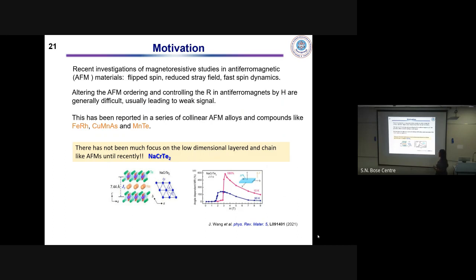One of the systems is NaCrTe2, where very recently it has been shown that under application of a magnetic field, a large magnetoresistance is observed because of spin flipping in this layered antiferromagnetic compound. So this prompted us to investigate magnetotransport in some layered antiferromagnetic systems also.